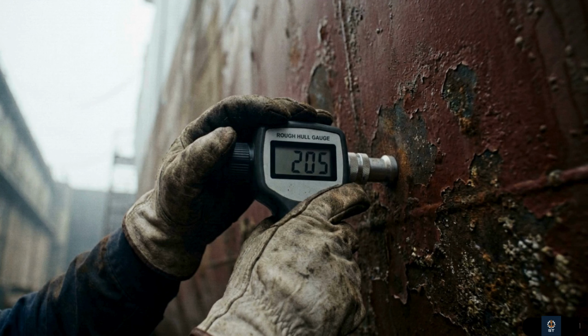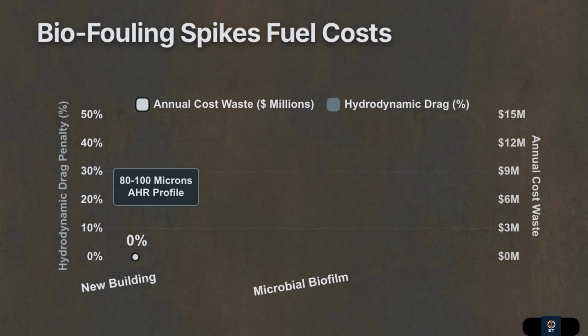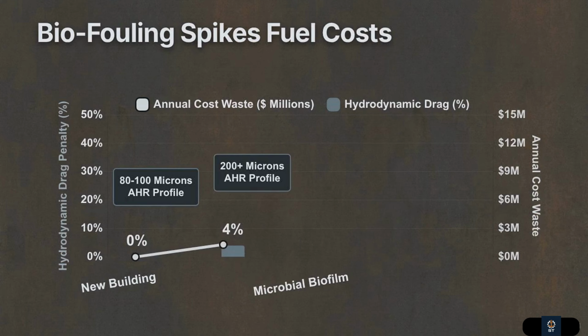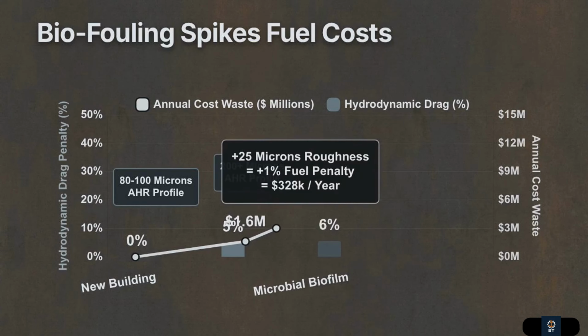This assessment is quantified by a metric called average hull roughness, or AHR. While a new ship leaves the yard with an AHR of about 80 microns, 5 years of ocean service can push that figure past 200, creating massive hydrodynamic drag. This microscopic profile tracks surface roughness. A 25-micron increase imposes a 1% fuel penalty. For a typical container ship, that wastes $328,000 yearly.